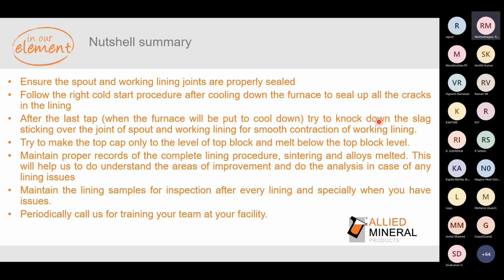After the last tap, when the furnace is going to be put into cool down, as I said before, try to knock down the slag sticking over the joint area of the spout and the working lining, so the lining contracts smoothly with no hindrance.